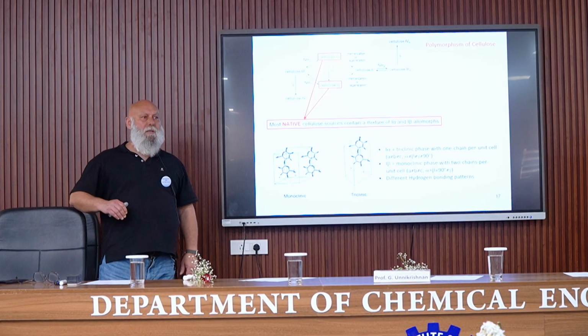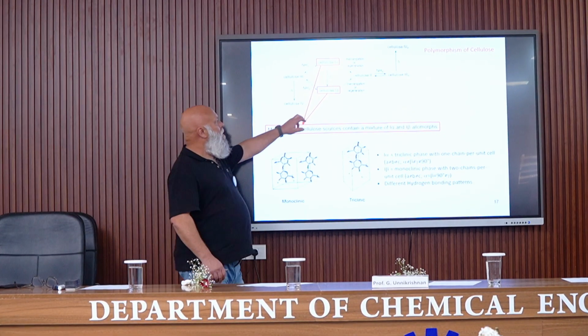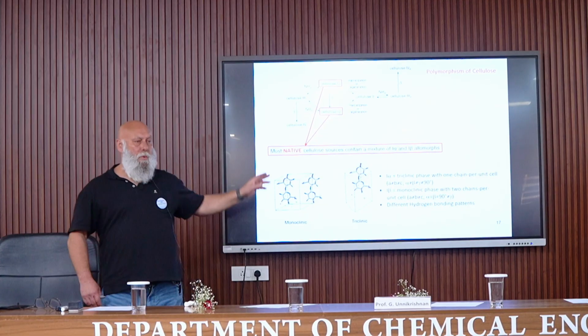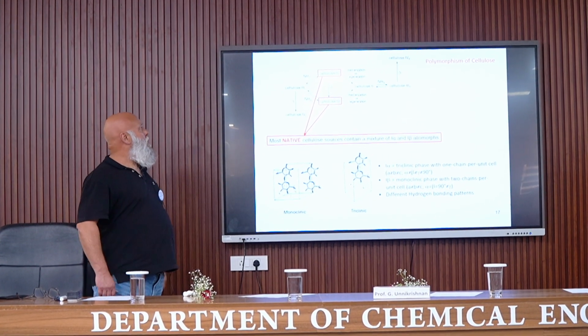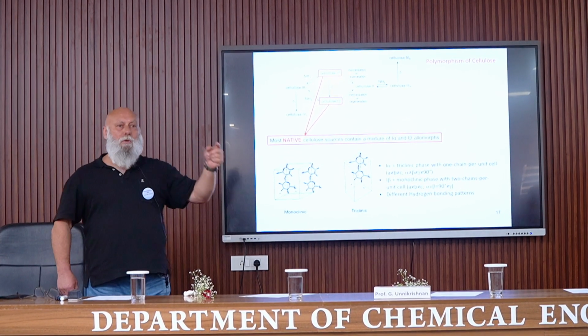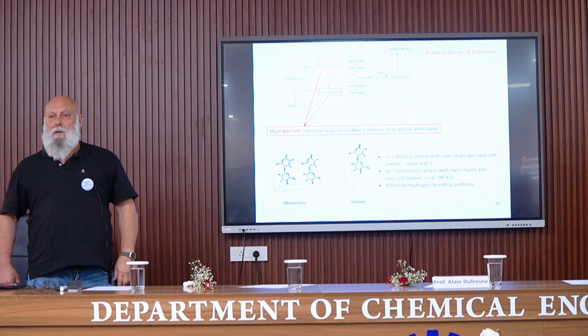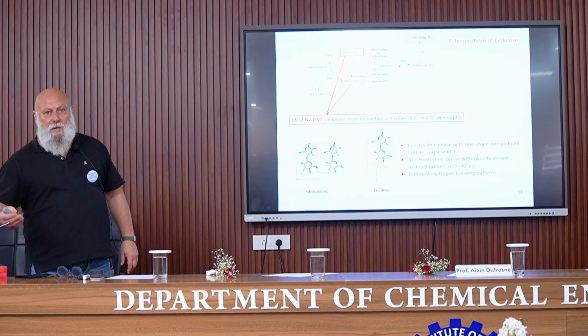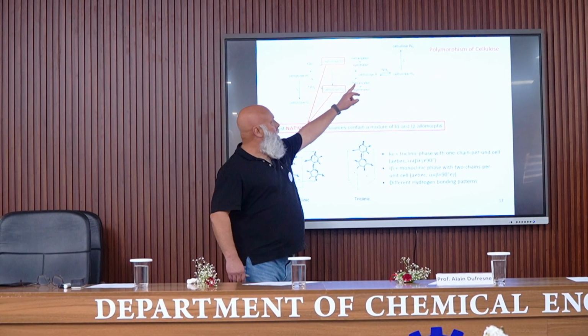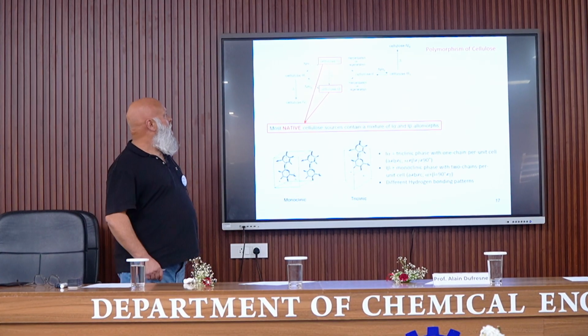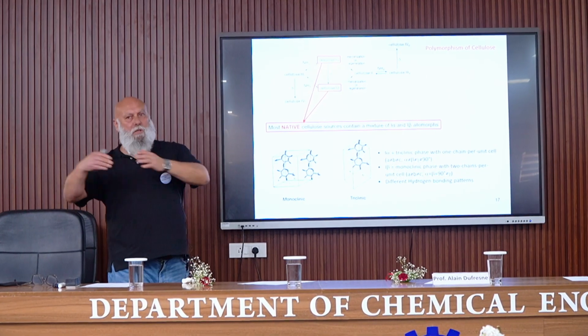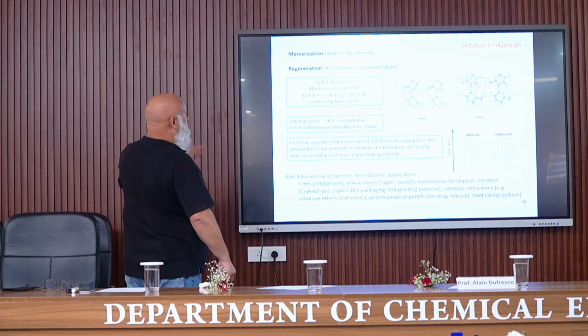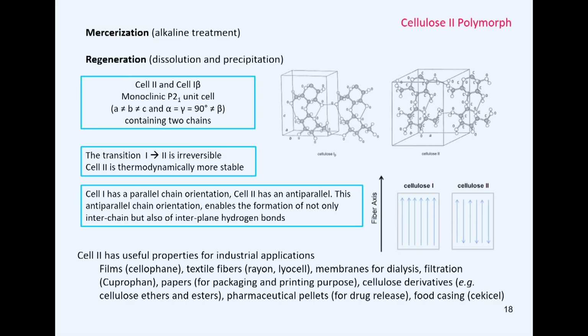It's possible to change this crystalline state to another one, which is called cellulose 2. This can be done by two processes that I will detail in the next slide, mercerization or regeneration. And this transition from cellulose 1 to cellulose 2 is irreversible, meaning that cellulose 2 is the most stable crystalline state of cellulose. Then by a treatment with ammonia, it's possible to convert cellulose 2 to cellulose 3, and then by a thermal treatment to cellulose 4, which is another crystalline form. So mercerization, which induces the transition from cellulose 1 to cellulose 2, is an alkaline treatment. And regeneration is a process that involves dissolution and precipitation. There are not many solvents for cellulose, sorry, but there are some.